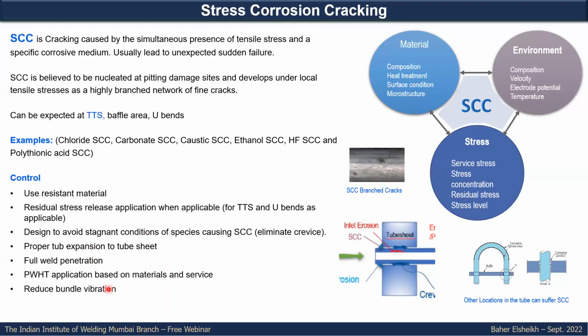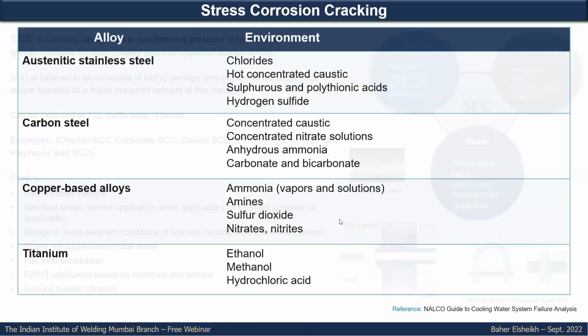Full weld penetration is highly crucial in avoiding that. Otherwise, the root pass will be an initiation point, like a crack initiation in many cases of stress corrosion cracking services. Also, from the service perspective or the design of the heat exchanger itself, you need to reduce bundle vibration or cyclic services. Otherwise, when the tube vibrates, all of these stresses will be transferred directly to the weld joint, leading to cracking or stress corrosion cracking.